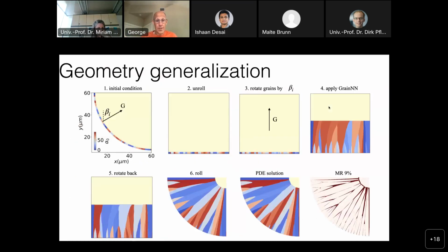But more interesting now, we can do melt pools, and that requires essentially taking an initial substrate distribution of the melt pool. There is a coordinate transformation in which we unroll this and we make it flat. It's a mapping of this quarter of a circle to a square. And then we have some parameter transformations in order to map the input here to the input to the rectangular domain. Then we apply GrainNN, and then we rotate back with some scalings, and we get the PDE solution.